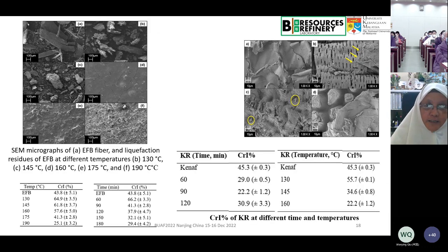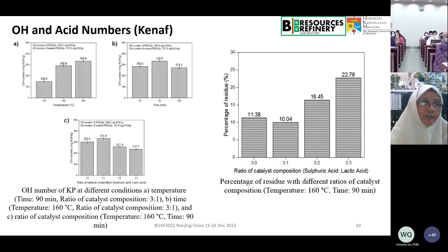And this is the surface structure of the residue, and you will notice that the crystalline area is decreased tremendously if you are measuring the residue here. It decreased with the temperature and also with the time taken for this particular liquefaction reaction. We also do the calculation for the OH number. We do titration, and you have an OH number as high as 300 plus for the Kenaf,